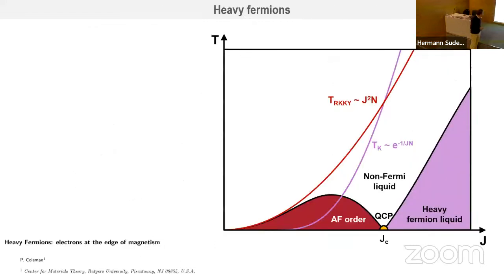Now, of course, you also have a lot of entropy. And there is one game which is important in this, but I won't go into much detail, let me just mention it. If you have F electrons localized in each place, you have to consider the exchange between F electrons. And there is a competition between the exchange, which gives you antiferromagnetism or ferromagnetism through the electron path, and the Kondo screening. And this competition very heavily dominates what happens in the physics of this material through this phase diagram, which is called the Doniach diagram.